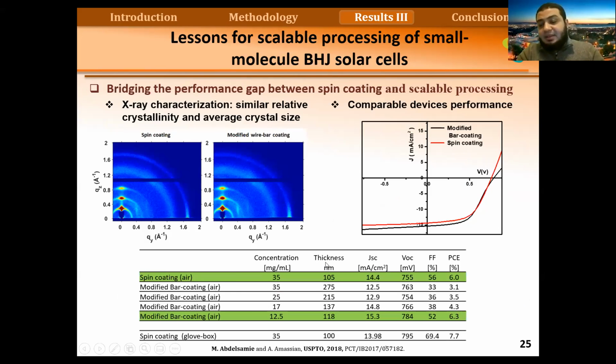And to prove that this is scalable, we have done the processing in air. Usually these are done in a glove box, which gives slightly higher performance because one of the layers that is used is reactive with moisture. So it has high performance in a glove box, but in order to prove that this is scalable, we have done all experiments in air, and we could get a relatively high performance for the modified bar coating.